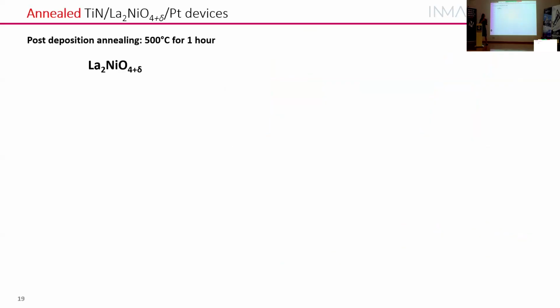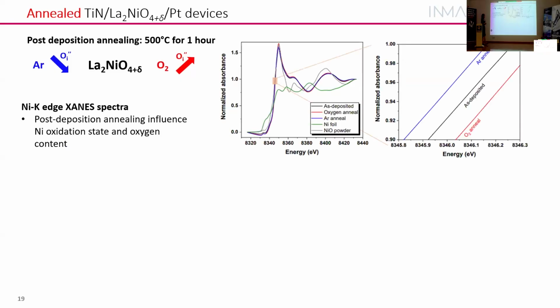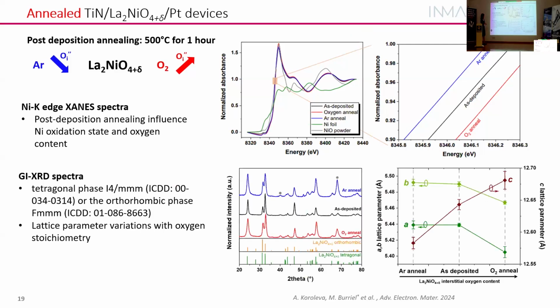So now I'm going to move to the next part. I'm going to explain, as I told you, we can play with the oxygen stoichiometry in these films. So we wanted to see what happened if we change it. If we do an argon anneal, we will reduce the oxygen content. If we do an oxygen anneal, we will increase the oxygen content of these devices. So that's what we did. Then we took them to the synchrotron to measure the nickel K edge. And we saw that the films, as expected, changed their oxidation state by oxygen anneal or argon anneal.